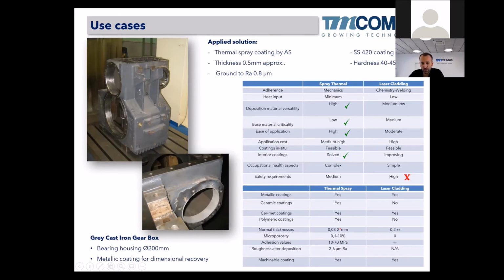The base material is not very weldable. It's a grey cast iron, so with welding we can have some problems. And especially because there are some restrictions here for the application. The cladding head would hit this part of the casing, so it's easier to use thermal spray, where you can have an inner coating gun, which is like a tube, so it's easy to approach this area. So the main reason was spatial restrictions and base material issues.